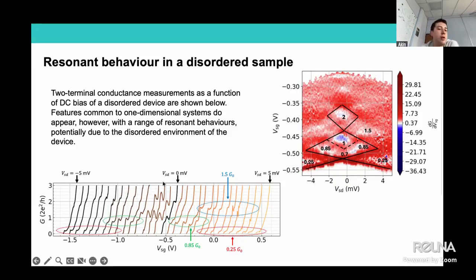One of them is a structure at 0.25 of 2e squared over h, which means that there is both a spin splitting, so spin degeneracy is lifted, and also momentum degeneracy is lifted. So if we were to think about how the current is distributed, there are moving states in both right and left directions of that one-dimensional wire. And as one increases the potential between source and drain, then maybe momentum degeneracy can be split. And then we see these reductions in features.